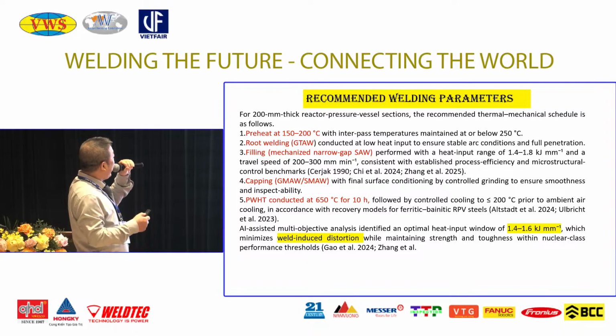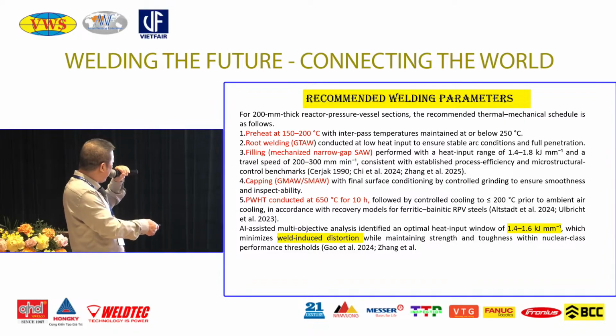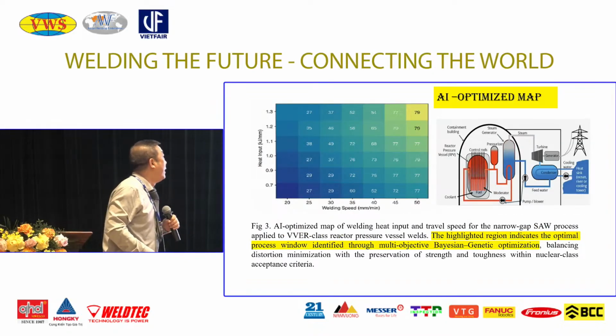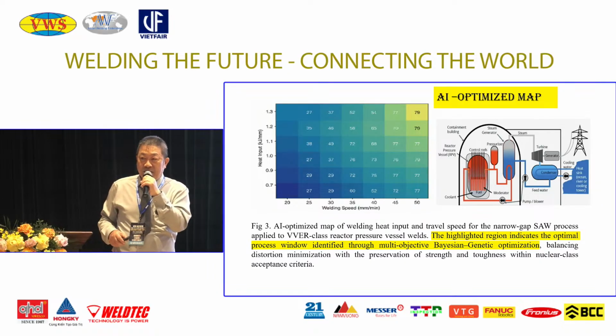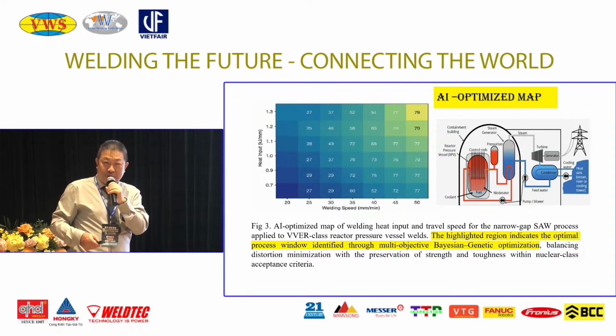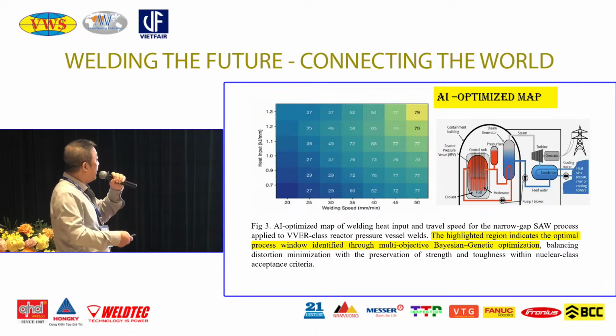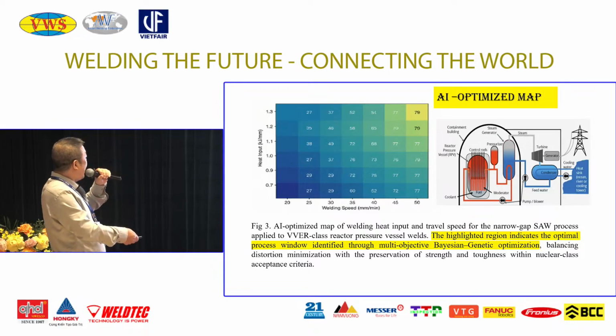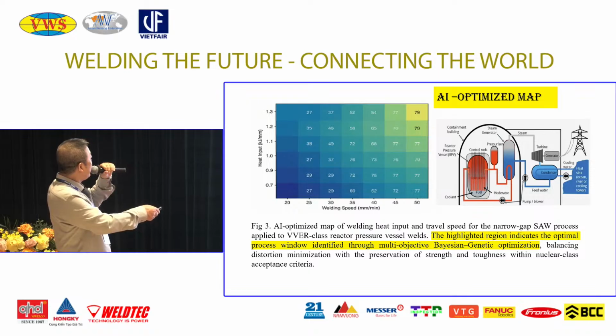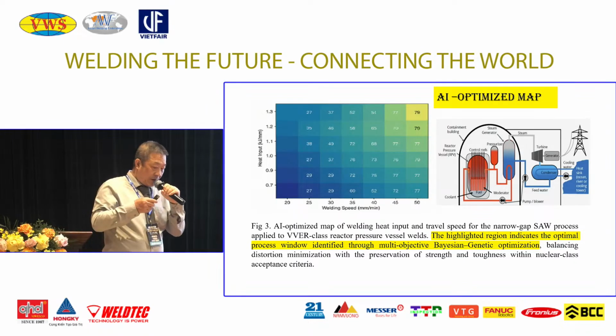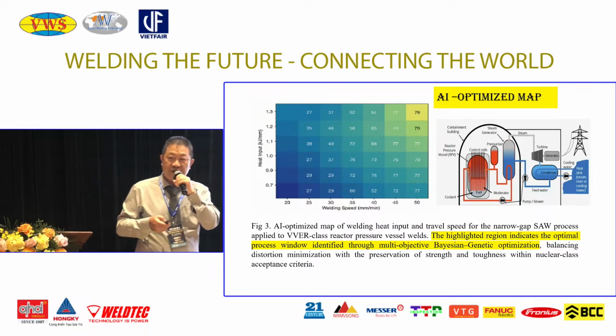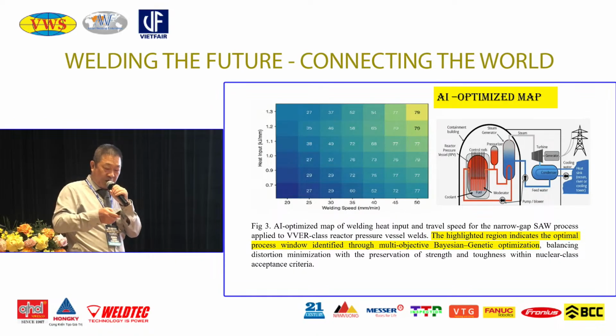Here are some recommended welding parameters, including preheat, root welding, filling, capping, and post-heat processing after welding. As I introduced at the beginning of my presentation, we are using artificial intelligence for predicting the optimized map of welding heat input, especially where we can choose this region, this area, welding speed and heat input to have the best structure of the welding joint after the procedure.